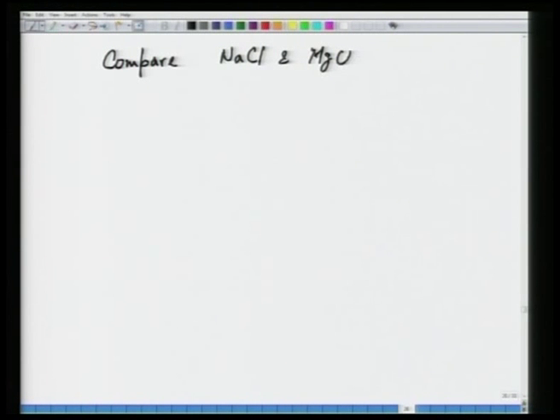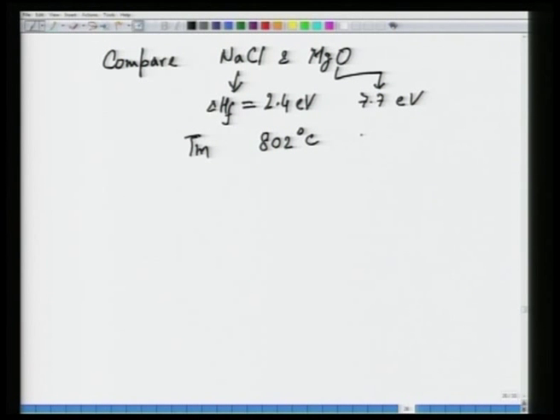For example, you can make a comparison between magnesium oxide and sodium chloride. So for instance, you can compare NaCl and MgO. So, for NaCl delta H f is almost equal to 2.4 electron volt, and in MgO it is 7.7 electron volt, and this is directly related to Tm. So, Tm of NaCl is about 802 degree centigrade, in case of MgO it is about 2825 degree centigrade, and you can see that MgO, being a larger melting point compound because of larger bond energy, has larger